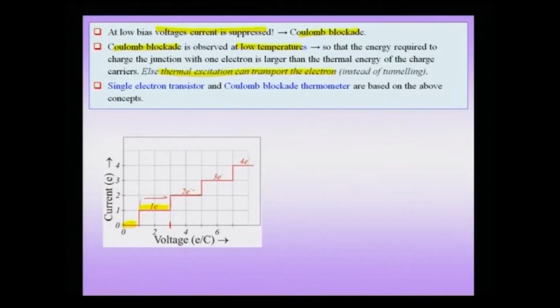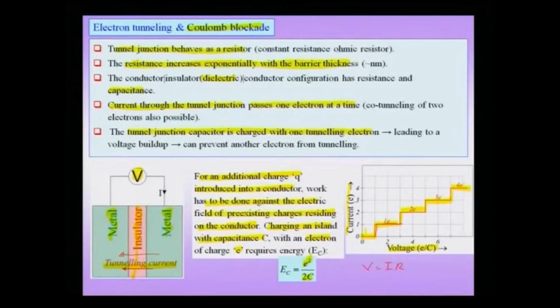This is a very interesting system, which has been put to use in developing devices like single electron transistors and Coulomb blockade thermometers. You can clearly see that there is no classical analog of such behavior in the voltage-current characteristic space, which comes from a thin insulator, in the nanoscale. At the heart of this whole process is tunneling current, which only happens in the nanoscale, and if I make a thick material, the tunneling current will fall to 0, because the resistance increases exponentially with the barrier thickness.